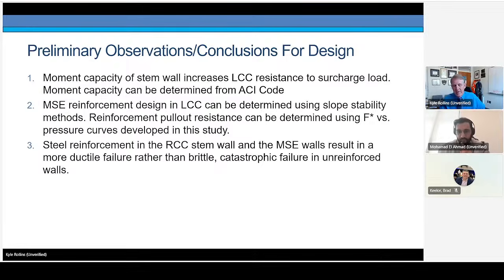Along with slope stability methods such as those in UTexas too. Having the steel reinforcement in the RCC stem and the MSE walls themselves result in a much more ductile failure mechanism in contrast to the brittle failure that occurred with unreinforced walls at a free face. So we think it's worth the money to put the reinforcements in place to lead to a ductile behavior rather than some catastrophic failure in unreinforced material.